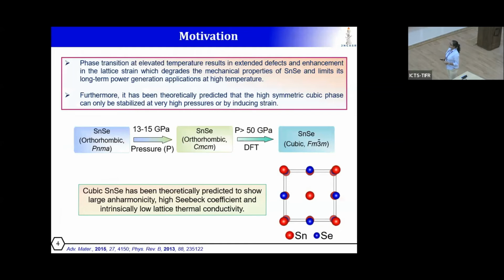So I have started to work on polycrystalline SnSe samples, and in this work I have also studied a way to stabilize the cubic form of SnSe at ambient conditions. In DFT calculations, theoretical studies have predicted that cubic rock salt SnSe can show a high Seebeck coefficient and low lattice thermal conductivity. But the problem is that the cubic structure can only be stabilized at a very high pressure of more than 50 gigapascal, which is really difficult to attain at laboratory scale.